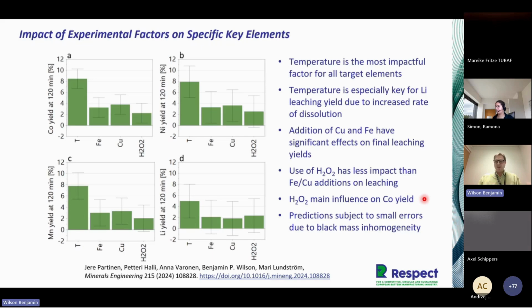But such predictions are subject to small errors due to the black mass inhomogeneity. Of course, black mass, normally in this case it was 111, but it comes from different input streams. So the amount of material in each yield varies somewhat based on that.